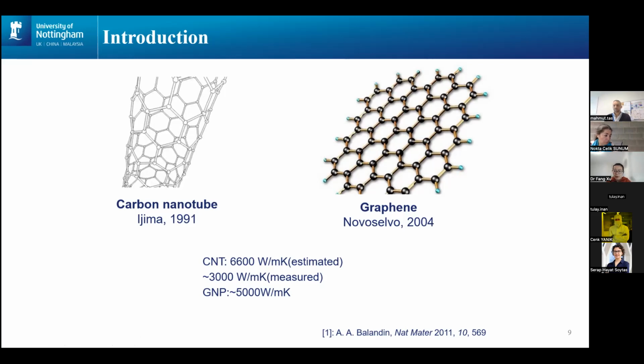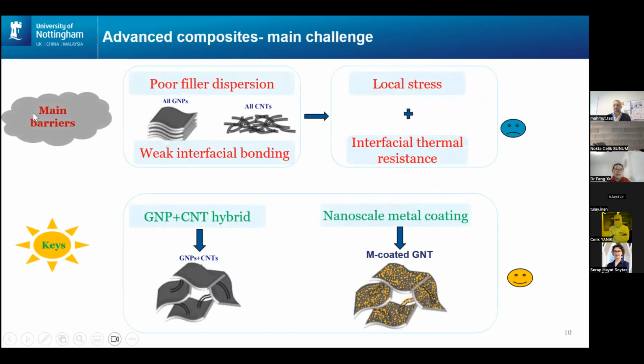If we look into more detail, we find that the main barriers are two-fold. The first barrier is poor filler dispersion, because of the pi-pi interaction between the different carbon layers and the van der Waals forces between the carbon atoms, so it's very easy for graphene or carbon nanotube to agglomerate together.